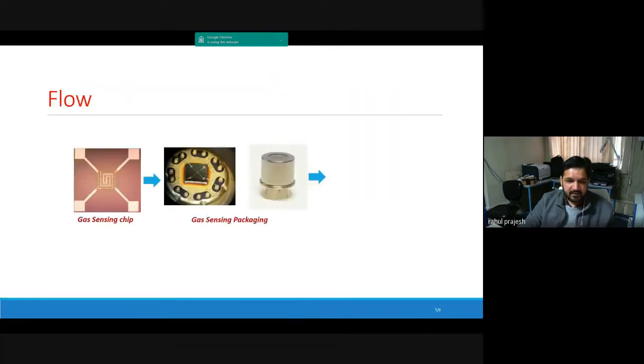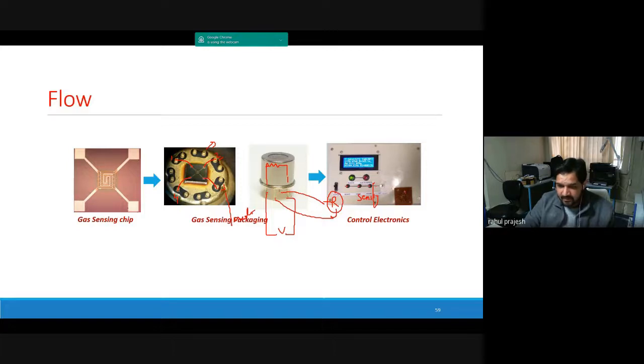Once that is done, then the device is kept on the header, as I have shown you. Like this is the header. On top of that, you keep the device, and then it is wire bonded onto the pins. Okay, like this. So these pins are wire bonded. Now you have 4 legs: 1, 2, 3, 4. Now you can make the connection from these 4 legs. So 1 and 3 are for heater. So you apply source here so that your heater is giving you some temperature. And then you have these electrodes where you measure the resistance of the sensing film. Okay. Then this device is interfaced with the electronics to measure the response of the device.